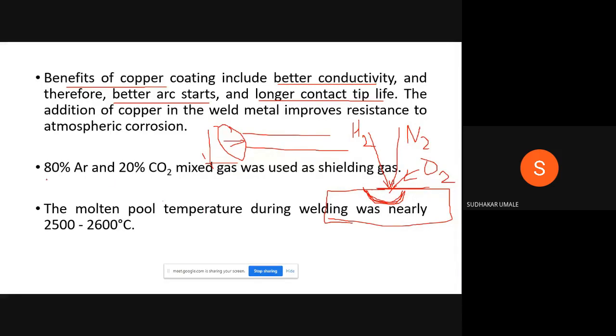And hence, we are using this mixture as the shielding gas, for protection of the arc: 80% argon and 20% CO2. CO2 is used because it is available very easily. 80% argon is not always available. If you keep 100% argon, no problem, but to make the conditions economical, we are using 20% CO2. The production cost will reduce.